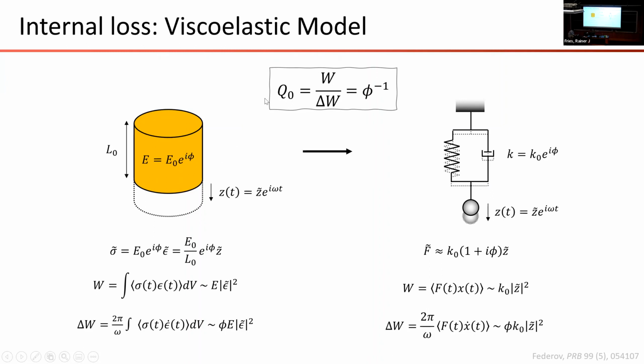So the quality factor of any elastic body can be characterized as the stored energy in a vibration divided by the energy loss per cycle, and it's completely encapsulated in this phase retardation, or this complex part of the elastic modulus. This maps directly onto the so-called Zener model of an elastic body as a mass-spring system, basically a mass suspended from a spring-dashpot. And this spring-dashpot in complex notation would just be characterized by a complex spring coefficient.